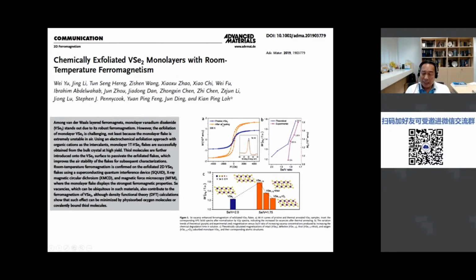But what was more revealing is that when they heated this VSe2, the magnetism became stronger, and they explained this by measuring the vanadium to selenium ratio. So for the ideal intrinsic pure vanadium Se2, the ratio of Se to vanadium is 2. But as they showed here, as they annealed it, in fact, they showed that what they actually grew was vanadium selenium 1.75. So there are possibly some vacancies or some loss of selenium in the growth process, which is not surprising since selenium is the more volatile element here.